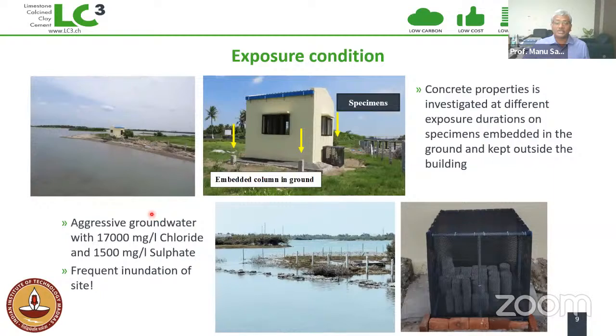Here, the exposure condition, as I said, is very severe. It's not directly in the tidal zone, or rather not subjected to the splashing of the waves, but still the location is in a very difficult condition. Here you can see that the backwaters can inundate this entire site. You can see during the time of construction the kind of inundation that happened in this picture. And the groundwater here, because of this inundation, has a very high chloride content, 17,000 milligrams per liter, and about 1,500 milligrams per liter of sulfate. So this is the condition in which the structure is standing.